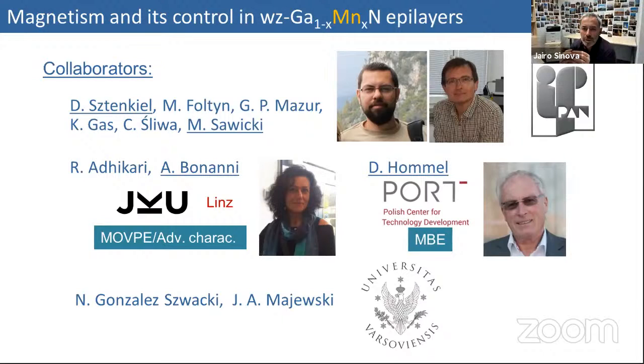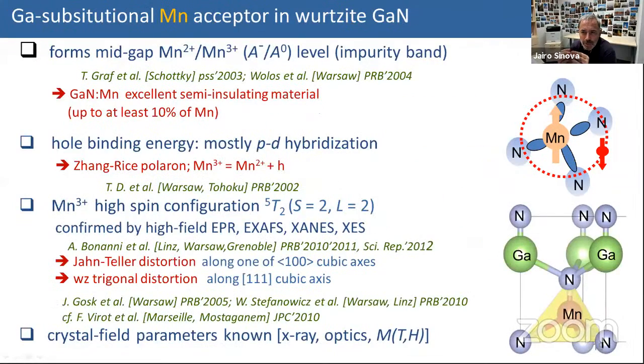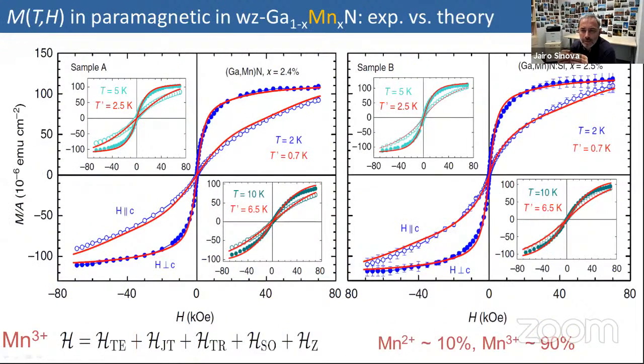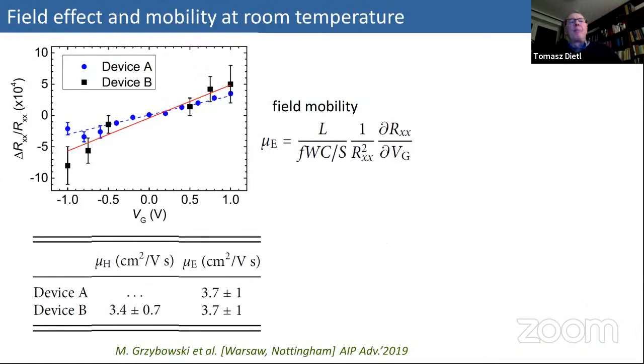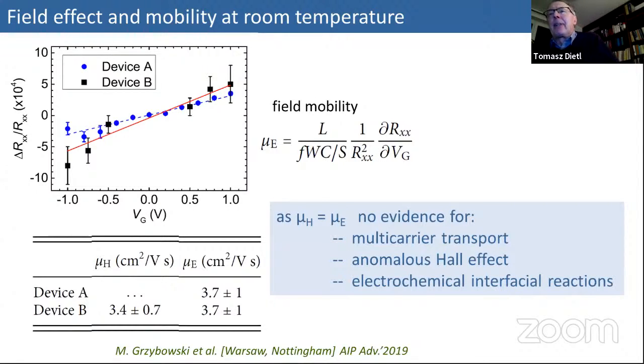I have a small question. So I guess in the copper manganese arsenide at the end, you said that you were trying to measure anomalous Hall effect? No, what I wanted to say is that a priori, what you expect in antiferromagnetic materials, that you may have difficulties with distinguishing between anomalous Hall effect and normal Hall effect, because both are linear in the magnetic field. In a ferromagnet, it's kind of easy because one depends on magnetization and the other on external magnetic field, and you can manage to distinguish between the two.